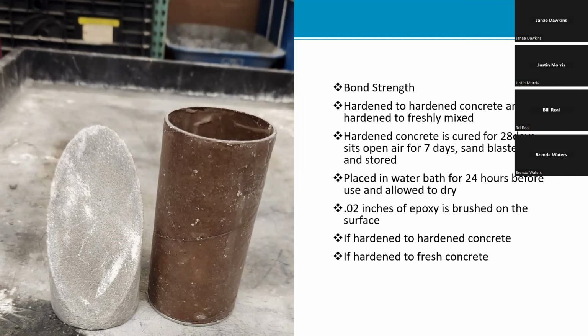Now it's at that point where you can sit it on a shelf and use it 1 month from now, 2 months from now, or however long it takes for you to be able to use the hardened part. Now, the epoxy that's brushed on this sandblasted surface is only 0.02 inches thick, and it's hardened to hardened concrete or hardened to fresh. If it's hardened to fresh, you'll have this hardened part already in the cylinder. Then you'll mix up your fresh concrete. Of course, your epoxy is already on the surface, and then you pour your fresh concrete into the cylinder and allow that to cure.